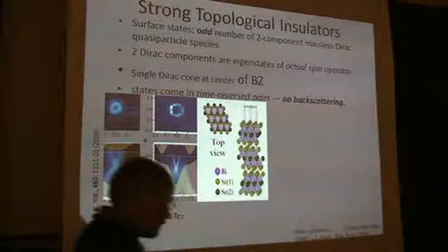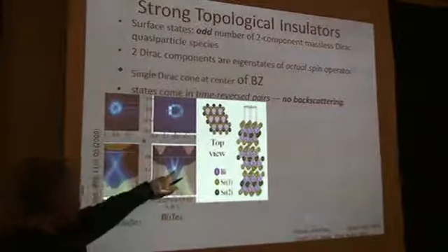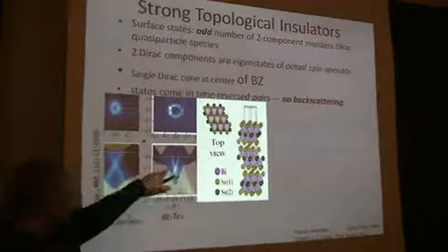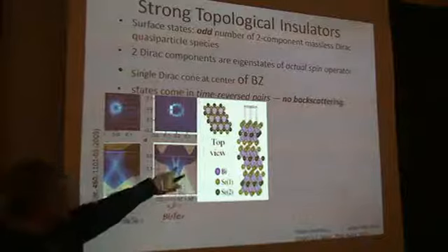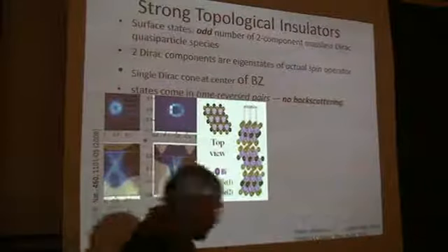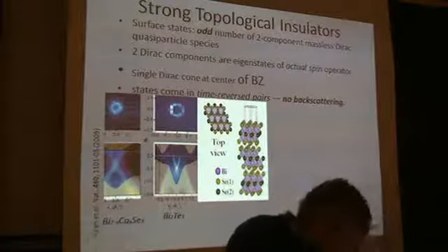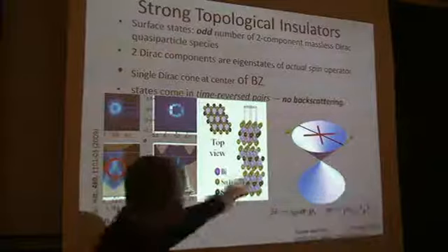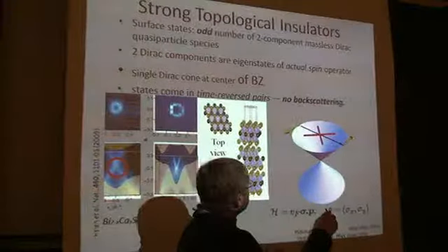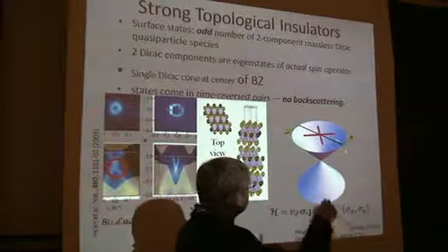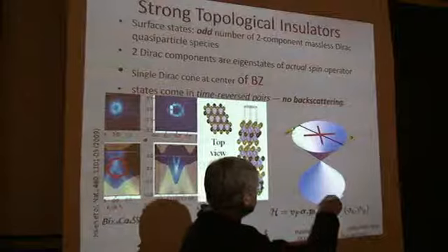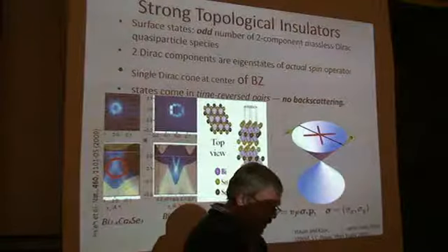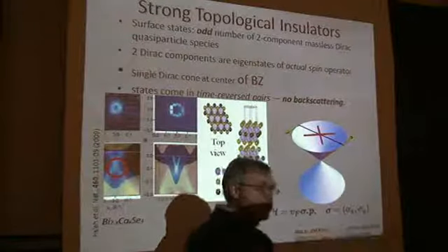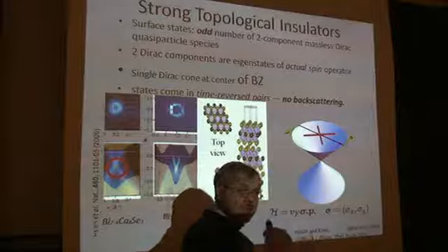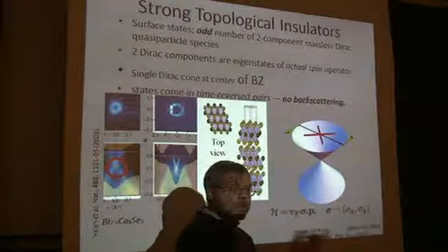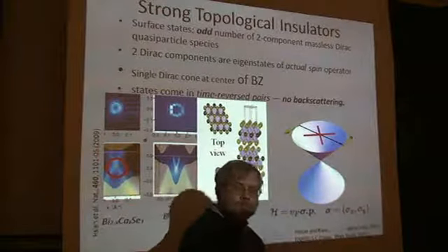Bismuth chalcogenide is here, and it's a more complicated one because the Dirac crossing point is sitting near the continuum. So it's much more challenging to separate the contributions from the Dirac and non-Dirac states. And as we've already discussed, the suppressed backscattering, as an input in the calculation for the T matrix, is certainly there. You have this cosine 2 theta dependence of the backscattering amplitude, which vanishes exactly at 180 degrees. But this is a non-trivial function of angle. It's not zero everywhere for all angles.